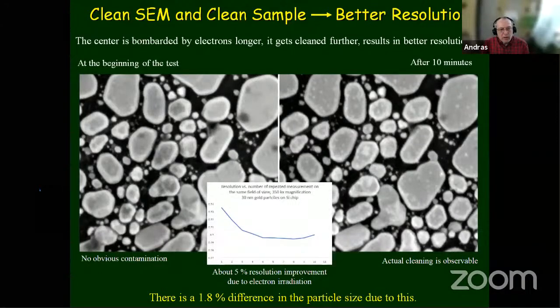So that insert shows a 30 nanometer size gold particle on a silicon chip sample, and you take an image, and everything is clean, the sample is clean and the instrument is clean, you evaluate the so-called resolution with this software, FEI Image or Thermo Fisher Image that I showed earlier. Then take another image and another image, you get improvement in resolution, about 5% further improvement, because the electron irradiation removes very tiny amounts of leftover material. So you end up with a cleaner surface. Why is this important? Because there's about 1.8% difference in particle size measurements due to this. So if you measure at the beginning and measure later after the electron irradiation of the sample, you will measure them smaller. Obviously, that's closer to reality. Next slide, please.